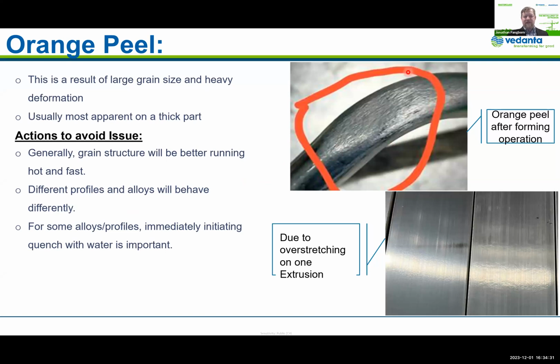So here's a case where it's very severe on a part that undoubtedly has large grain structure and also has a pretty good bend on it, but it can be even due to stretching on the press line. Here's an example of a normal one, you can see a little bit of grain deformation, but for most parts it's not excessive. And right next to it, and I don't know why this happened, but undoubtedly there was a difference in grain structure. Maybe they had a delay in the process or something. The adjacent part in the rack has grain structure, and it clearly has larger grains.